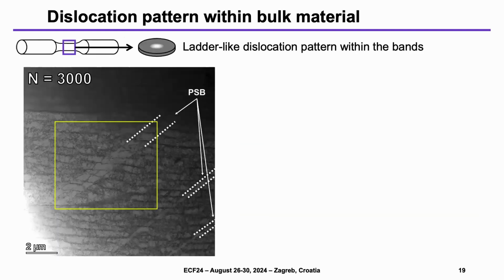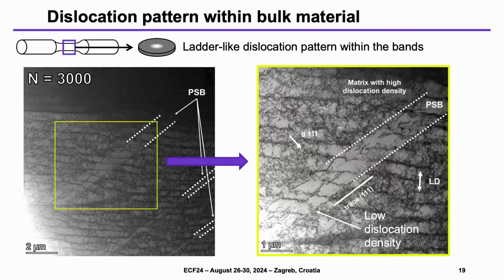So using TEM, we were able to identify the bands. And as you can see, maybe here it is better, the bands are characterized by a low dislocation density compared to the surrounding material. And they are also characterized by a kind of ladder-like dislocation pattern. This is similar to conventional FCC metals. However, in this case, the walls of the ladder-like pattern resemble the surrounding material cell structure, which is characterized by the initial cell structure.